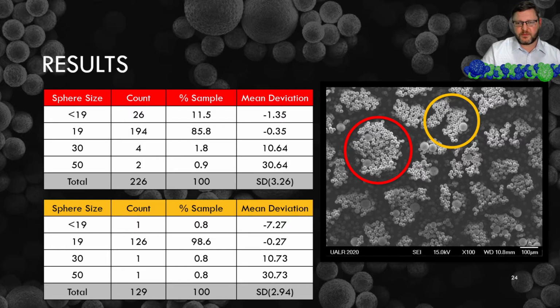Okay, results. So this image to the right, what I did is I drew that red circle. I counted every sphere that is inside that circle. I got 26 spheres that were less than 19 microns in size. I got 194 that were 19 microns in size, 4 that were 30 microns, and 2 that were 50. So 86% of the sample is essentially the exact same size.